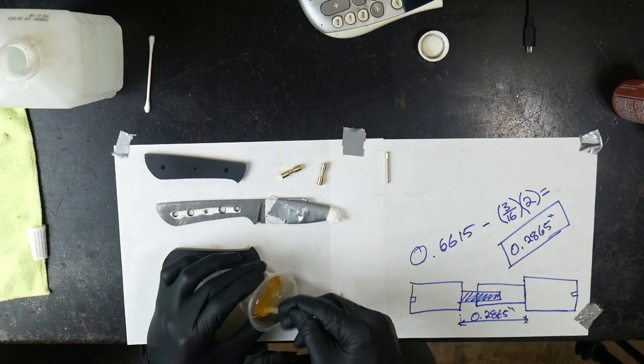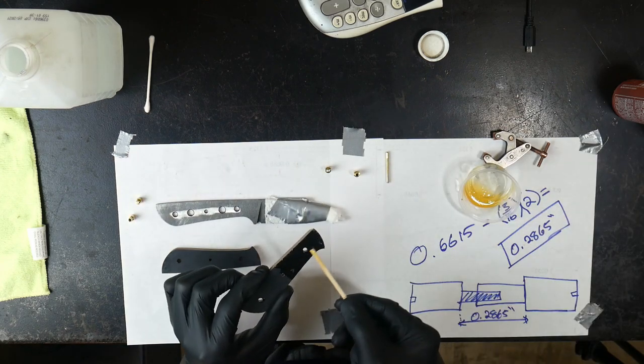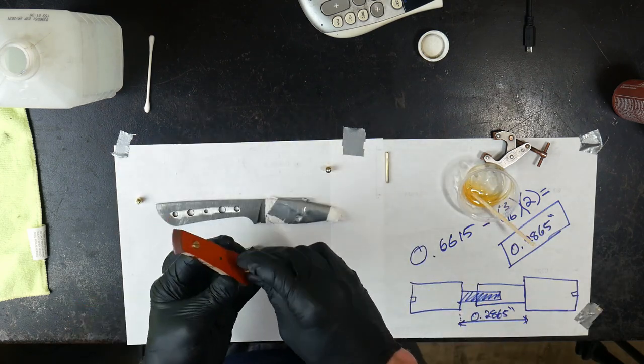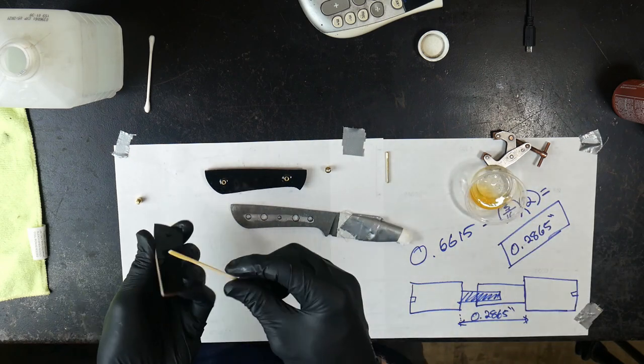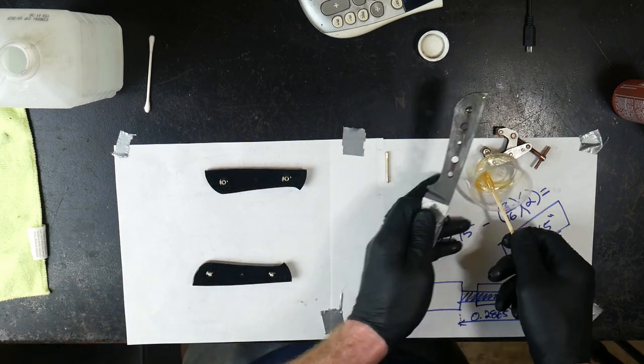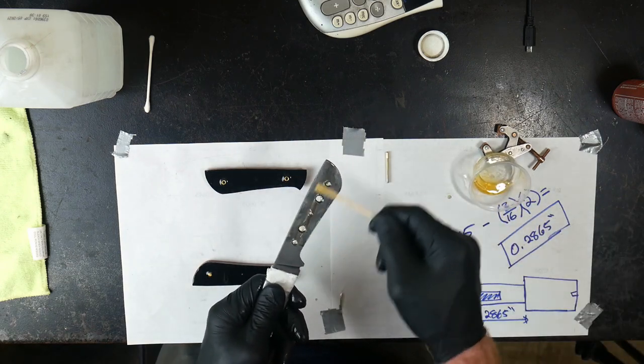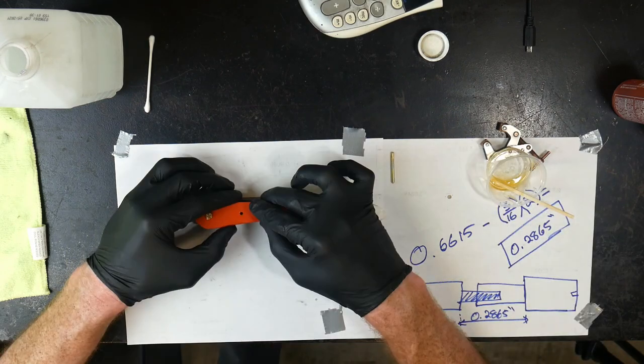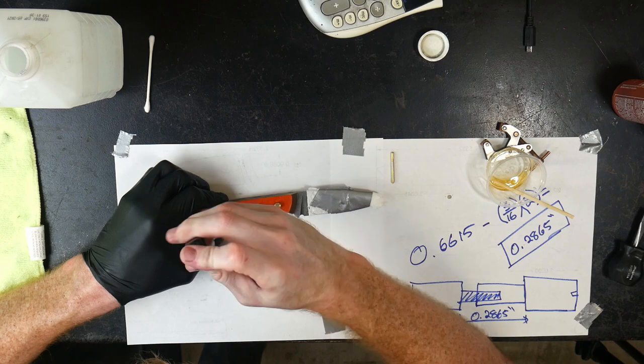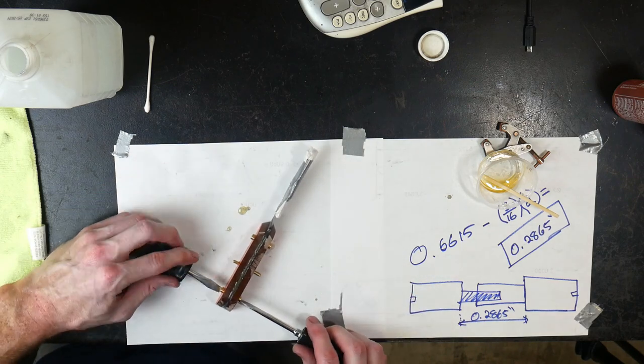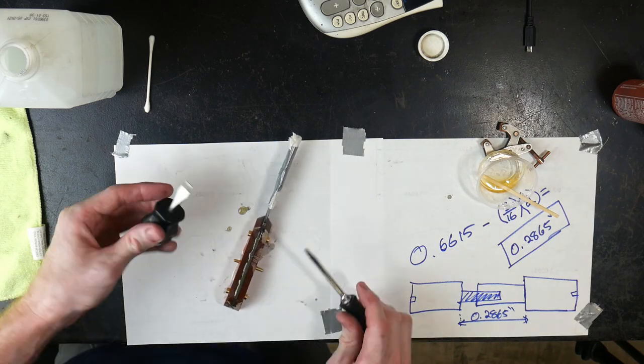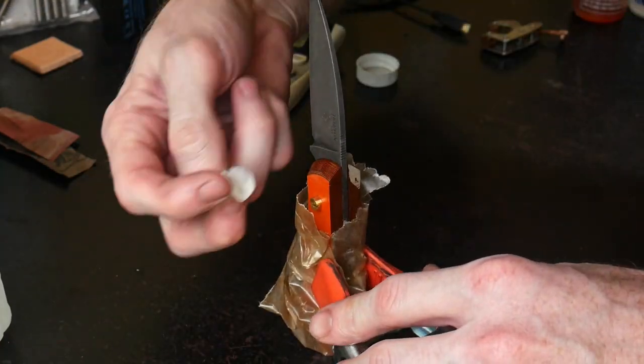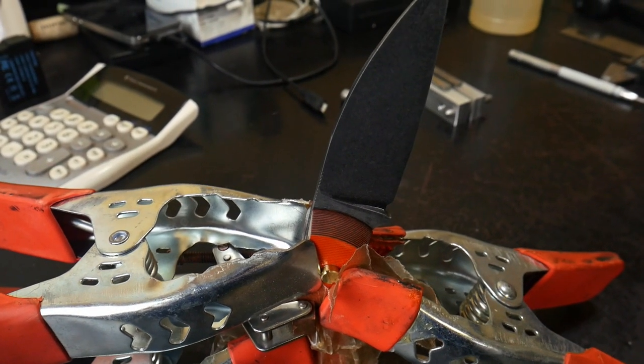Using some G-Flex epoxy, we get it nice and mixed up. I think I normally mix up about 1.6 grams of each container there, and that's more than enough to glue up a knife. I put a little bit of epoxy into the Corby holes first, coat the flat of the scale, put the Corby fasteners in, do that on both scales, and then put the epoxy onto the knife itself, making sure to fill up all of the epoxy holes that we put in there in the tang, get my Corby fastener started, and then pop that 1/8 inch pin in there before tightening down. I like to have that 1/8 inch pin in there first, just so that when I'm squeezing the scales with the Corby fasteners, that epoxy can go all around that pin and all the voids inside of the handle.